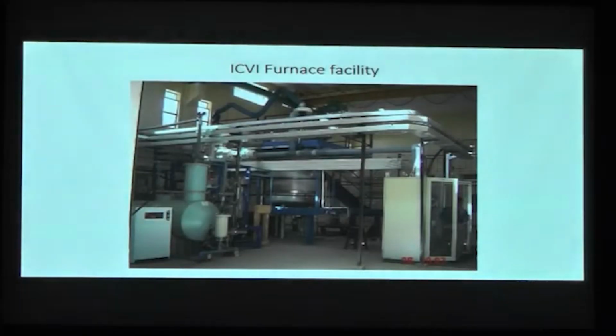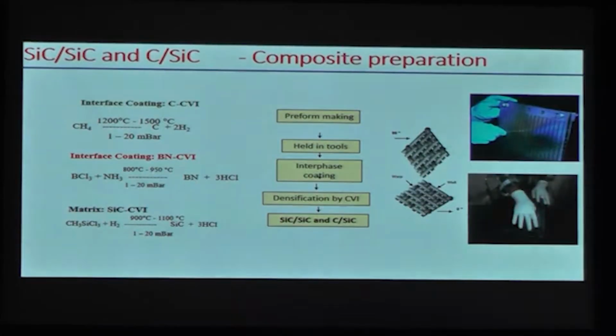So this is the CVI reactor facility which is available at CSIR NAL, established in 2005 with the support from DRDO to the tune of 8 to 9 crore, which has a temperature capability of 1400 degrees centigrade and pressure capability of 1 to 300 millibar. And this is the typical process.